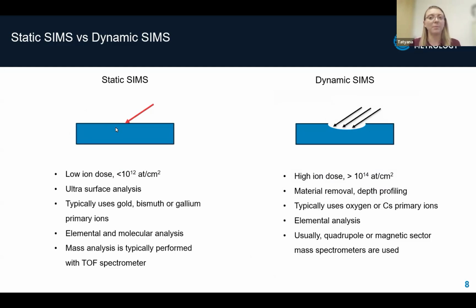SIMS measurements can be performed in two different modes, static and dynamic. Let's take a look at the key differences between them. On the left, we have static SIMS. This method uses a very low ion dose, less than 10^12 atoms per square centimeter. Because of this, it's great for ultra-surface analysis. Typically, we use primary ions like gold, bismuth, or gallium. For mass analysis, we rely on a time-of-flight spectrometer, which gives us both elemental and molecular information.